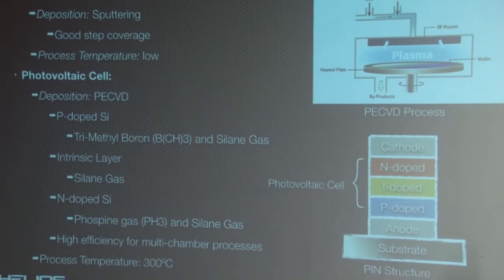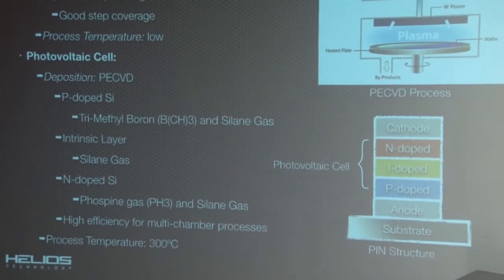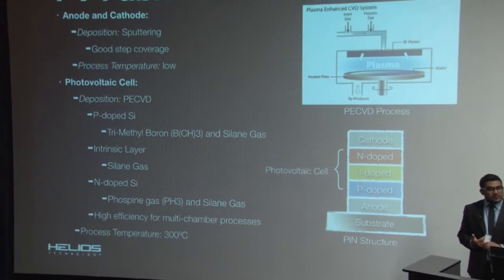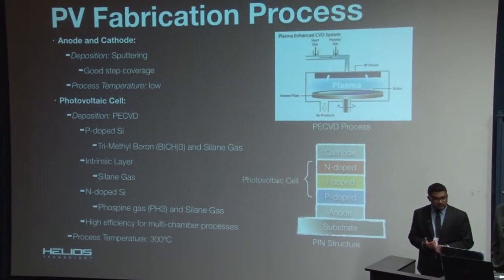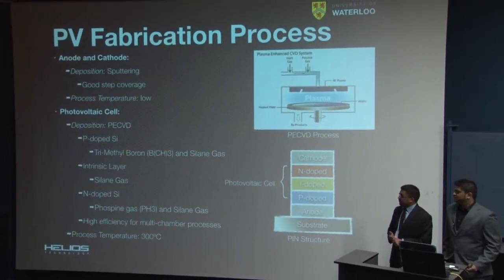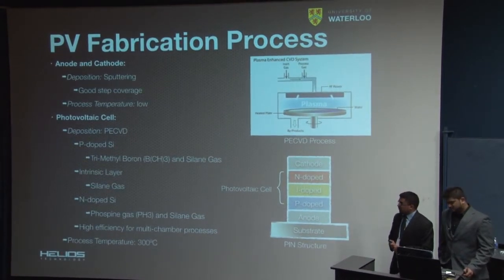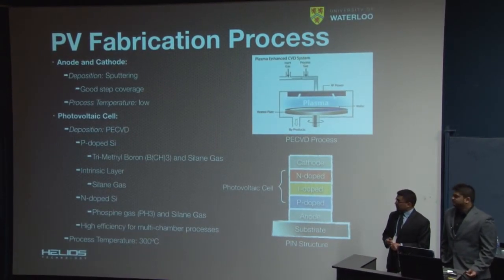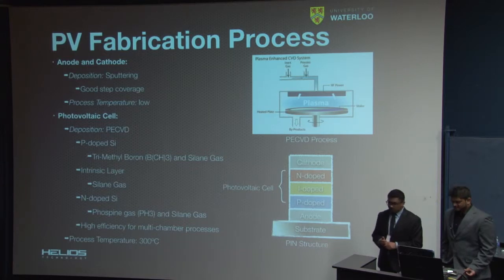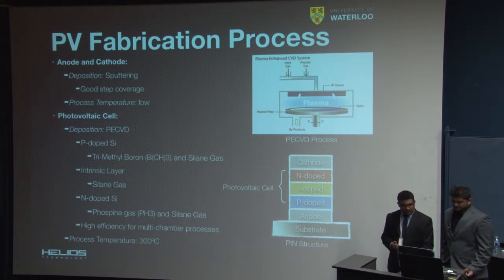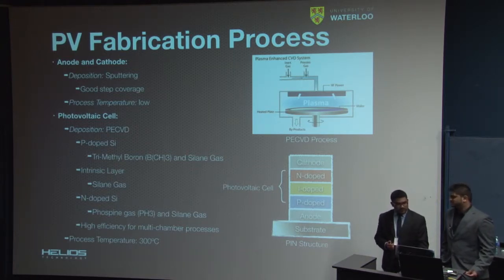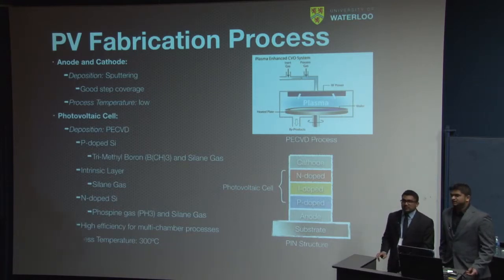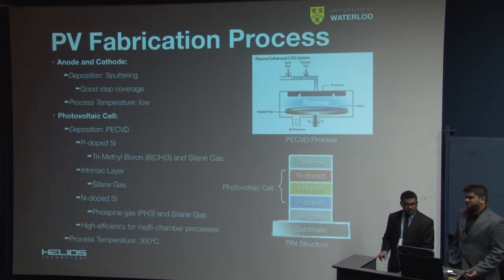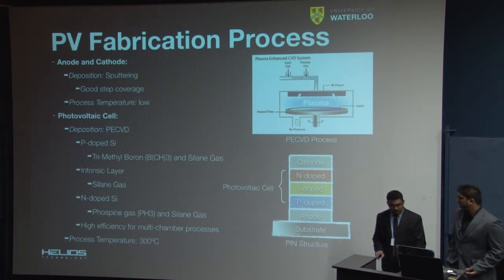The photovoltaic cell itself is amorphous silicon. It was deposited using PECVD, and we did the p-doped silicon by introducing trimethyl boron and silane gas. And then the n-doping was done through phosphine and the silane gas again. We chose this process because it has high efficiency for multi-chamber processes, and it works at a process temperature of about 300 degrees C, which is ideal for the materials we're using.